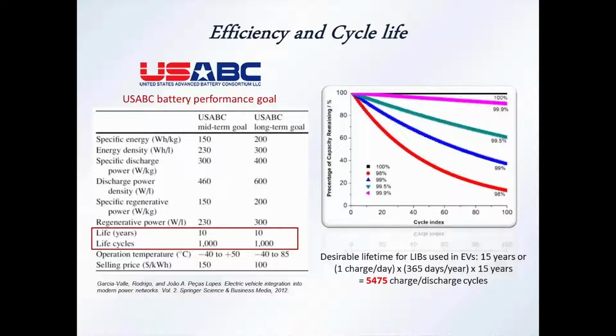On the right-hand side, it shows the percentage of capacity retention upon cycling for the first 100 cycles only. We can see that even for 99% cycling efficiency, it's not sufficient for us to get enough capacity retention, even for only 100 cycles. There's a criterion for defining battery failure for automotive applications. It's 80% capacity retention. If you draw a line at 80% capacity retention, we can see that even 99.5 or 99.9% is not sufficient. That's why cycling efficiency is important.